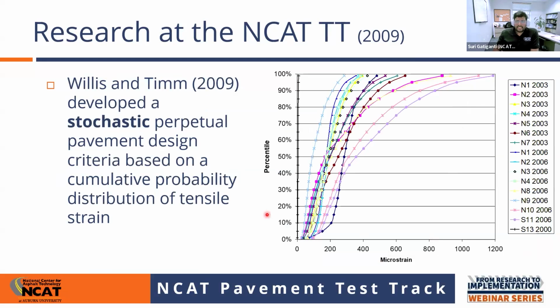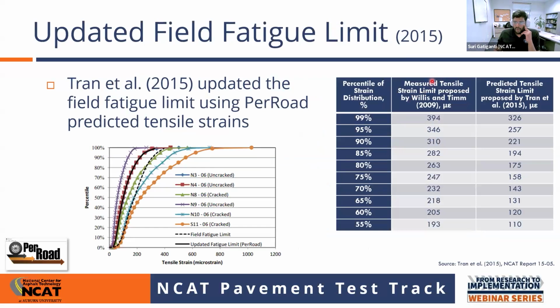So what they came up with is basically there is no single strain value that we can design our perpetual pavements with. It's a distribution. So if you see, the x-axis is basically the tensile strain at the bottom of the AC layer that we were measuring at the NCAT test track using the strain gauges, and the y-axis is showing the cumulative distribution. All the sections that produced strain values lower than that dark solid line never saw any fatigue cracking. But sections that experienced higher tensile strain values than that red solid line experienced bottom-up fatigue cracking. So those two demarcating points helped us come up with what is called the measured tensile strain criteria proposed by Dr. Richard Willis and Dr. Timm back in 2009, based on field measured strains.